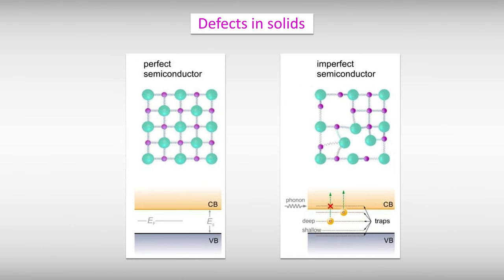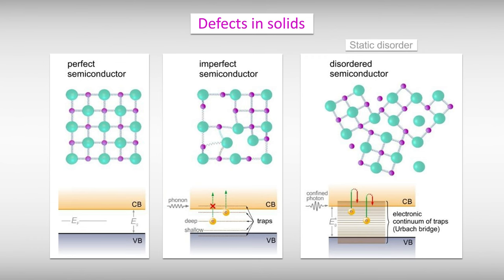And still, what role does the optical nano-antenna play in semiconductor photonics? There are no perfect crystals in nature, and therefore, their lattices are distorted with defects – vacancies, other atoms, interstitials, etc. – which introduce static disorder into the system. A question is being raised: can disorder or chaos play a positive role for improving electron and optical properties of solids? Transforming a crystal into a disordered state or glass creates a huge amount of multiscale structures. Each of them can function as an optical nano-antenna. I would like to remind you that amorphous silicon absorbs light 30 times better than crystalline one. So, this means that glass can be used for generating confined photons.